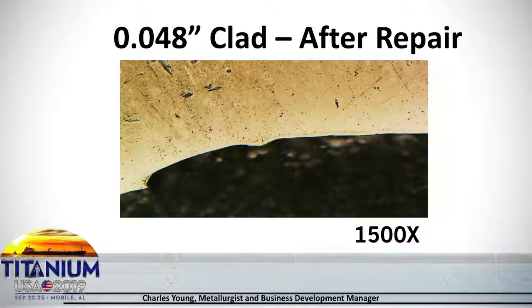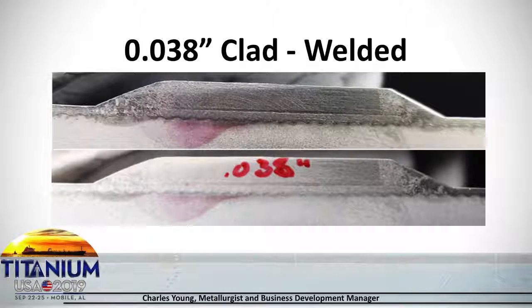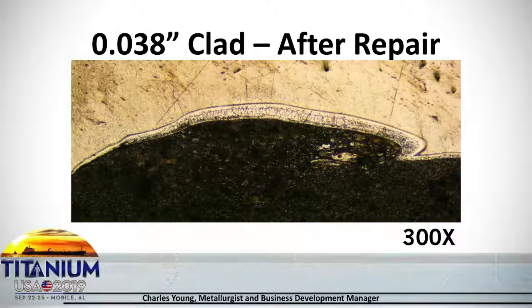Again, another picture at a very high magnification. You can see the oxide that's developing because of the heat of the weld. Now on this one, on 038, you're actually seeing some very good indications of heat in that steel to titanium zone. And if you look at it under the microscope, you can definitely see some titanium and iron intermixing here. So you're getting to a point where the clad metal itself is not going to be as viable as it was initially.